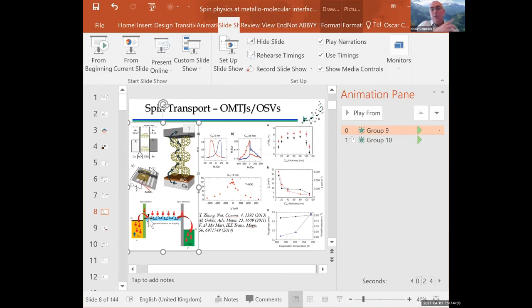So that's why in the case of C60 you can have 100 nanometers of C60. I don't know how many hops that will be, let's say of the order of 100 or 200 hops, before you actually lose all your spin polarization. And then they drop into the second electrode through the Schottky barrier that is going to be between the molecule and the second electrode, the semiconducting-metal interface. Does that answer your question?